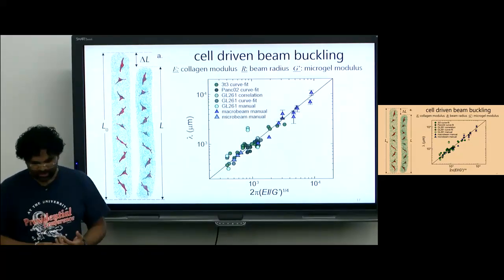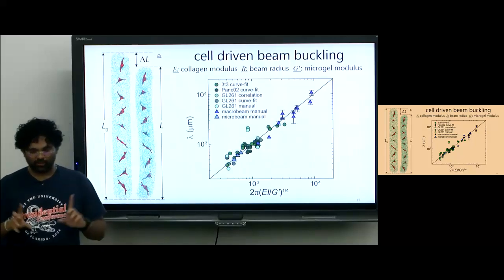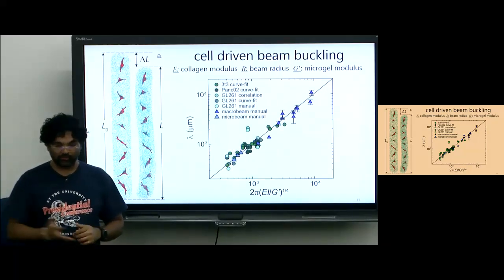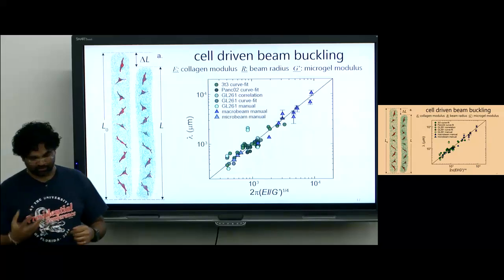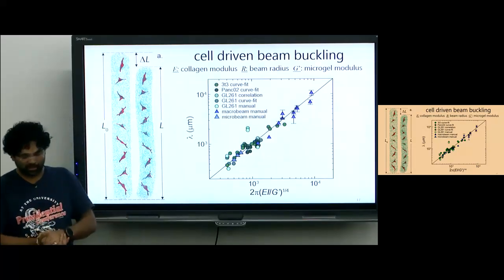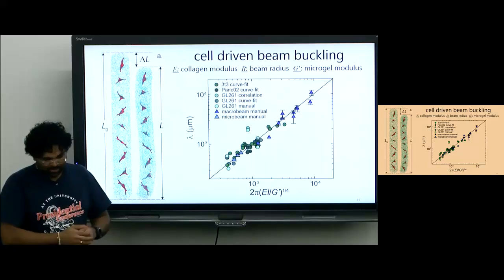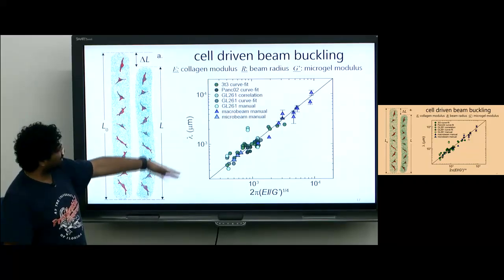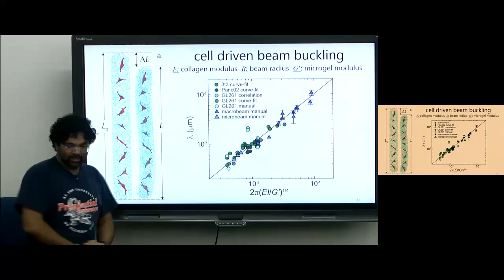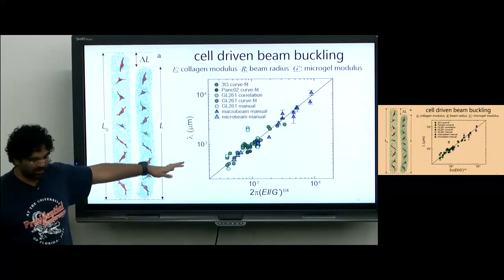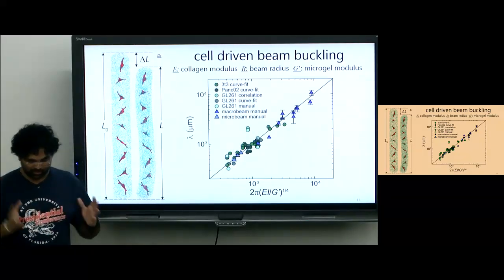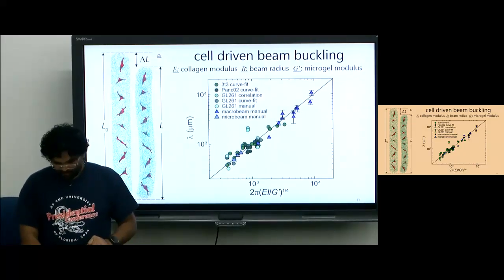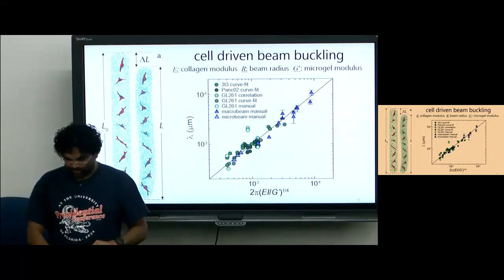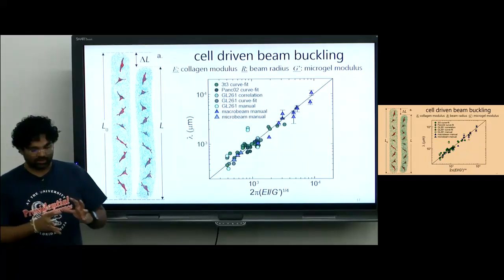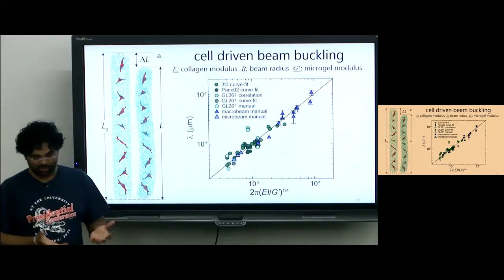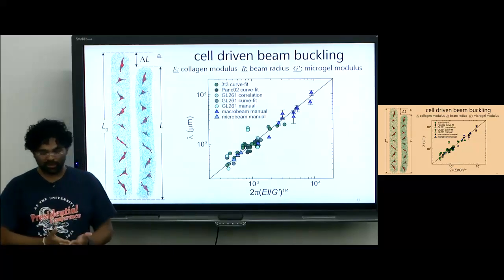By doing this across an entire range of diameters and different types of beam printing, the wavelength of this buckling was characterized using Euler-Bernoulli theory, which is again the mechanics of a beam supported on an elastic substrate. Again, this follows this nice little trend. The data was not fitted; this is raw data, and it all lies on this nice curve. It was found that the Euler-Bernoulli theory predicts this data of undulation of these beams with essentially no fitting parameters.